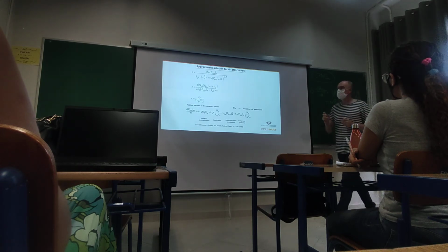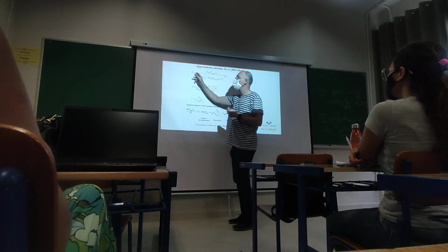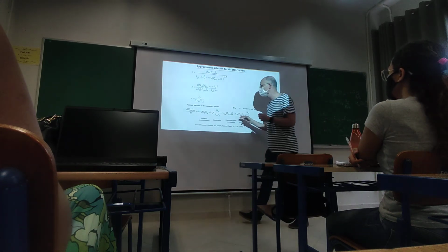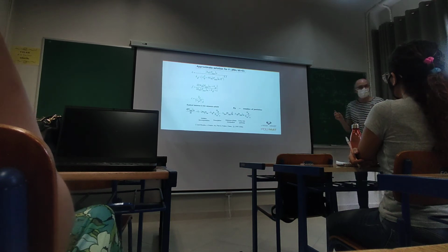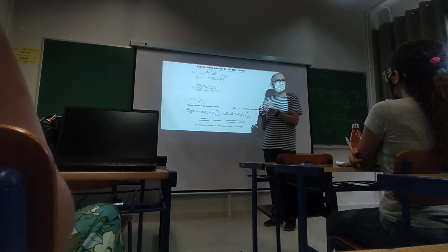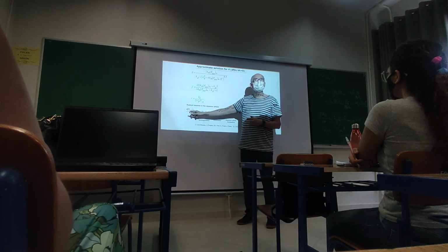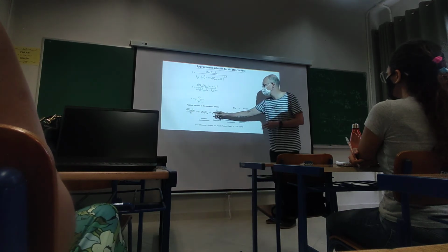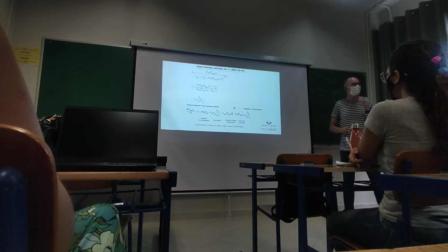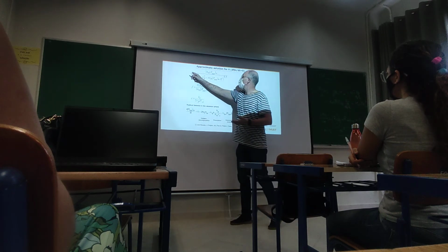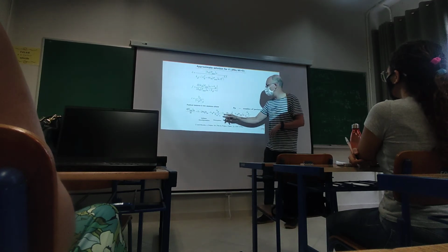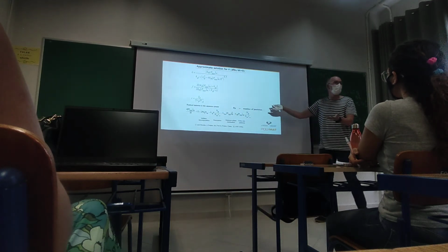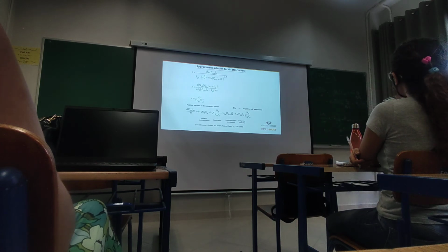So to calculate N bar, we have to solve this equation together with this one. But here, someone has been quick enough to realize that to calculate this, we need N bar. So we have a problem. To calculate N bar, we need P dot. To calculate P dot from this algebraic equation, we need N bar. So the only way to solve this is to do an iteration.